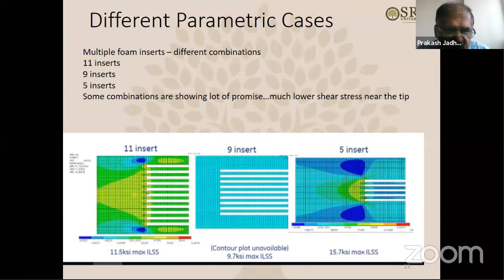So we tried like 5, 9, and 11 foam inserts, and we found that it did show some promise. It showed much lower shear stress near the tip. Okay? Because instead of a single big one, you are distributing the foam inserts into multiple embedded foam inserts like this. So your weight reduction target will be achieved, and as well, you don't see the stress concentration as high as you've seen earlier. This is what the target was.